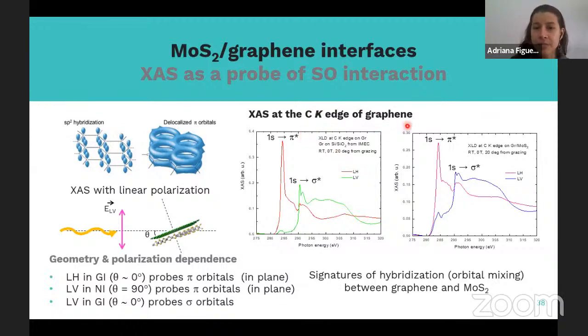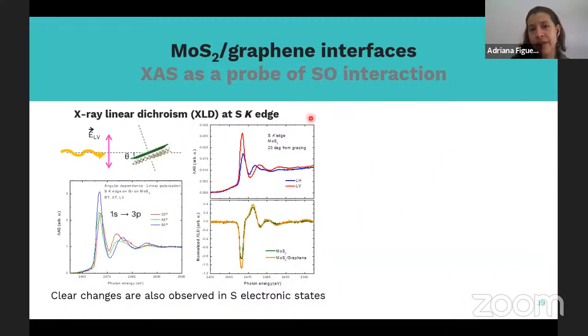Looking at the carbon edge, we use linearly polarized light in order to probe the different orbitals that comprise these graphene layers, because depending on the geometry and the polarization, we are more sensitive to one orbital or the other: one orbital that is more out of plane, and the pi orbitals that are in plane. We see strong changes in the spectra between bare graphene and graphene interfaced with MoS2, which means that there are signatures of hybridization as a result of orbital mixing between the graphene and MoS2. We also did something similar at the sulfur K edge.